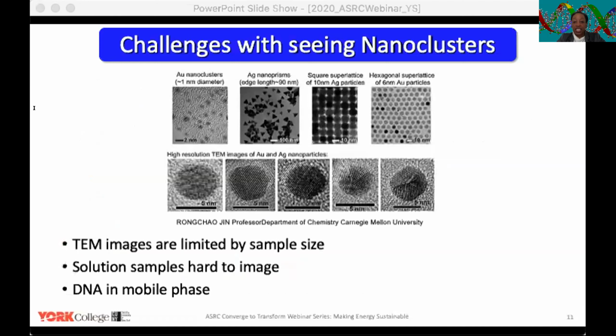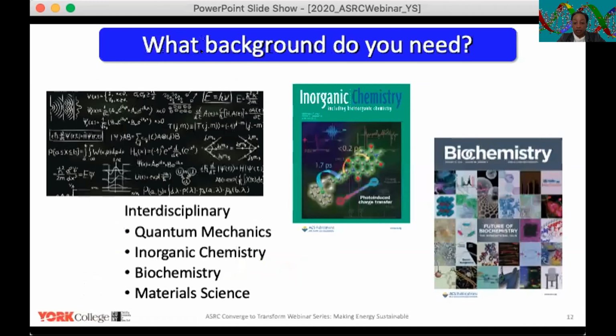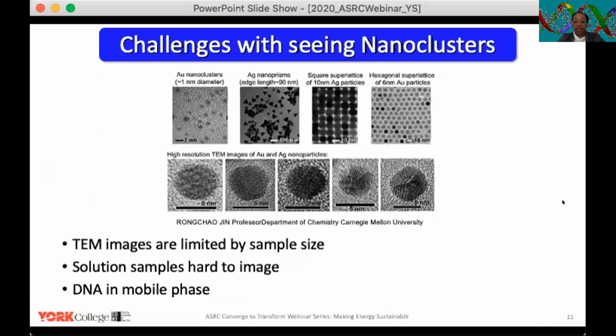So some challenges, here are some STM studies and TEM studies of, for example, gold and silver nanoparticles. And so these are nice clear images of what's going on, but when we've done AFM and TEM on our system, they're much more murky, because once the DNA is scaffolded to the cluster, it's hard to distinguish where the DNA ends and the cluster itself begins. And in that small size regime, it's uncertain.